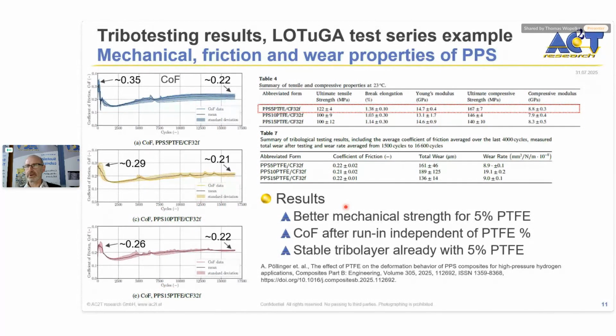As you can see, in the running-in process, we had a higher coefficient of friction for the low PTFE concentration, but throughout the test, the coefficient of friction was evolving in the same way. So at the end, there was no difference at all anymore. We also measured the wear of the polymers at the end, which could not be distinguished statistically.